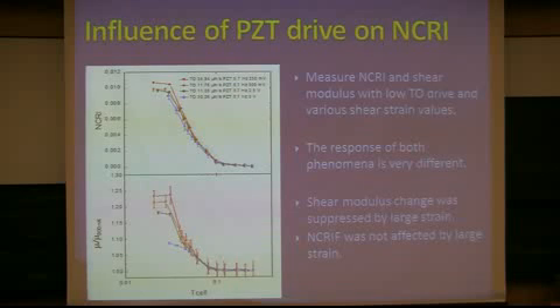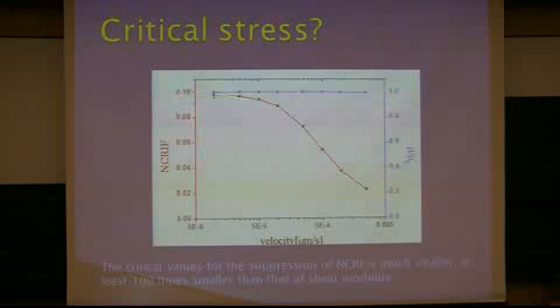However, I'm not satisfied enough. So I just did the measurement the other way around. In this case, I changed the shear modulus by shaking the shear transducer really hard to make it softer. So the shear modulus was suppressed by like 60%. Any change in the non-classical rotational inertia? No obvious change. And if you plot the change in the NCRI and the change in the shear modulus as a function of AC velocity or shear stress level, then the critical stress is very different. They cannot be the same. They cannot have the same microscopic origins.